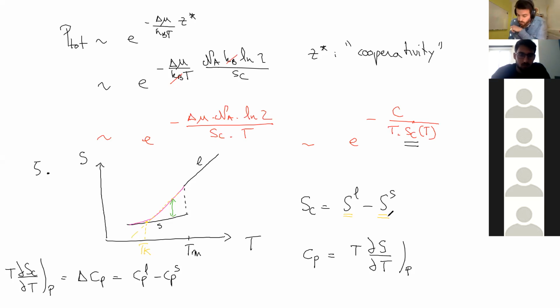Therefore, if there is a point at which the configurational entropy becomes smaller than 0, so the entropy of the liquid becomes smaller than the entropy of the solid, there should be something happening here, a phase transition. We should change completely the physics. So Kauzmann, based on those drawings, said there should be a finite temperature at which there is a real phase transition going on. Nothing about dynamics. I mean, a fundamental change of properties of the system at equilibrium.